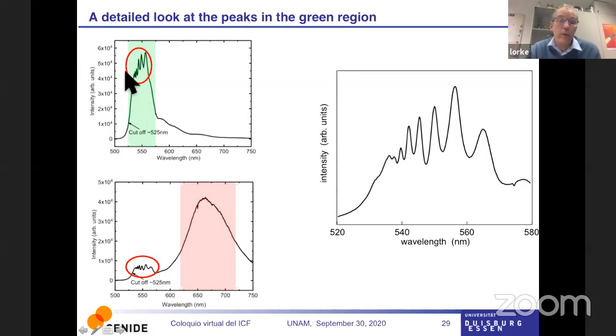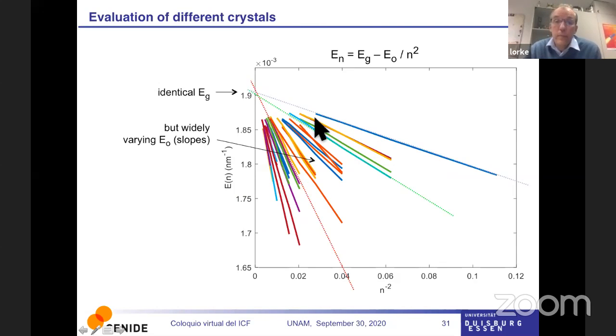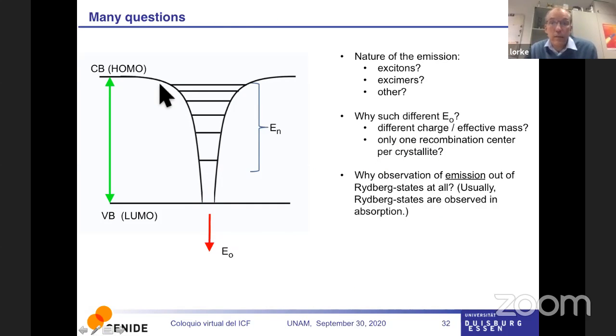If you do spectroscopy on semiconductors and you look at what energy you have absorption and emission, that's the band gap. And so all these lines extrapolated for n equals infinity to one energy that I have already called the energy gap. And that was exactly the energy gap that we saw from these other experiments, where we just looked at where emission starts and absorption ends. So it was very tempting to say, well, yes, this is something like a Rydberg series of, let's say, a dopant, or maybe it is an exciton.